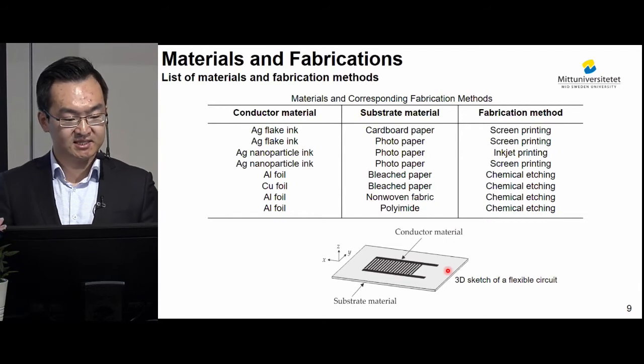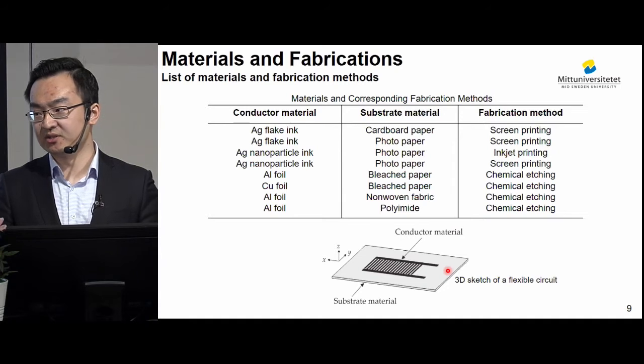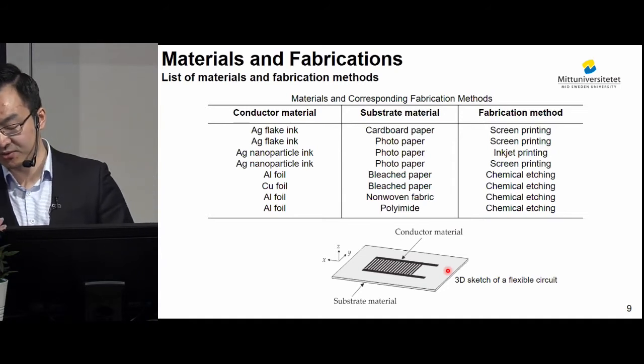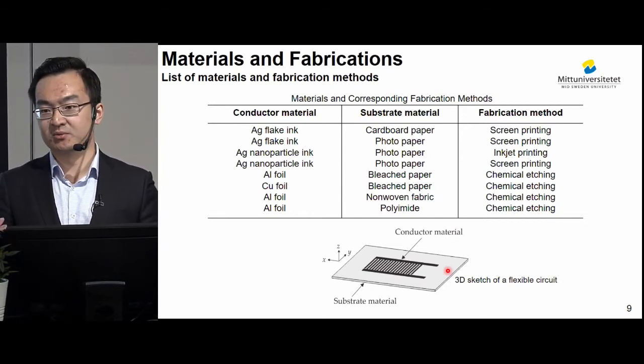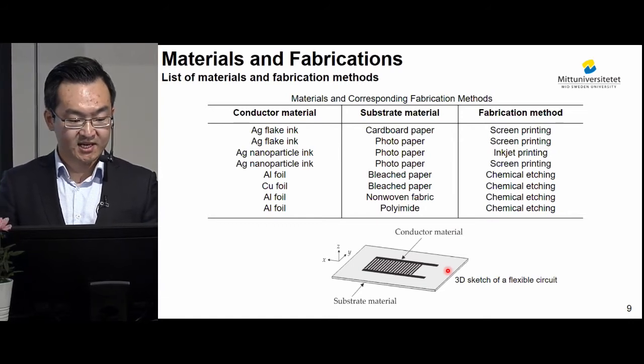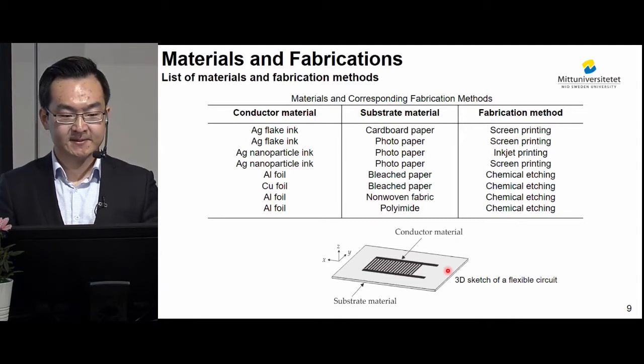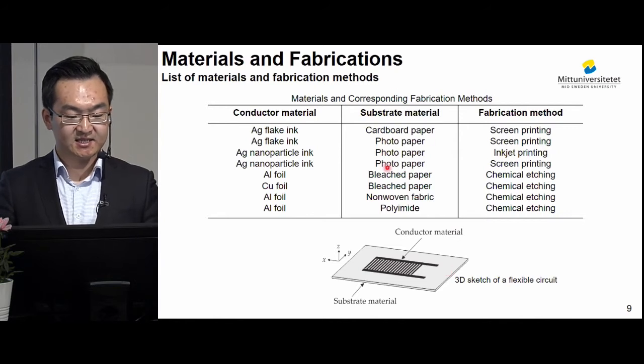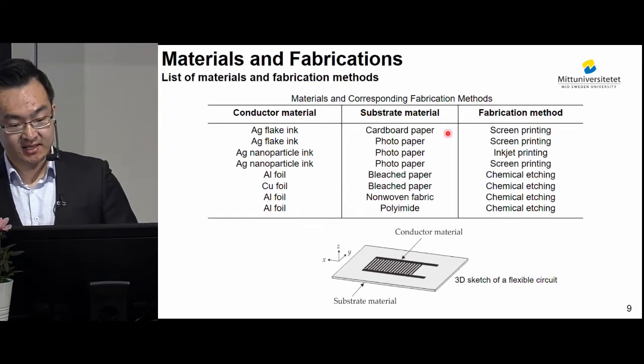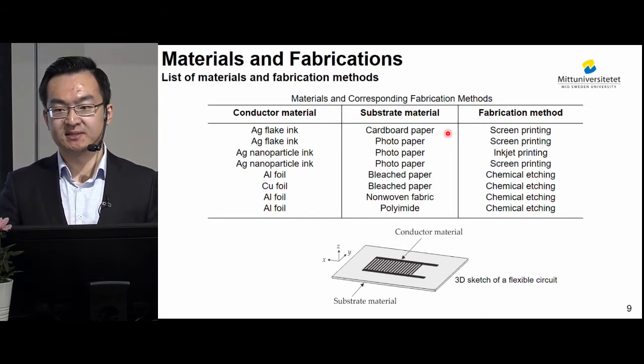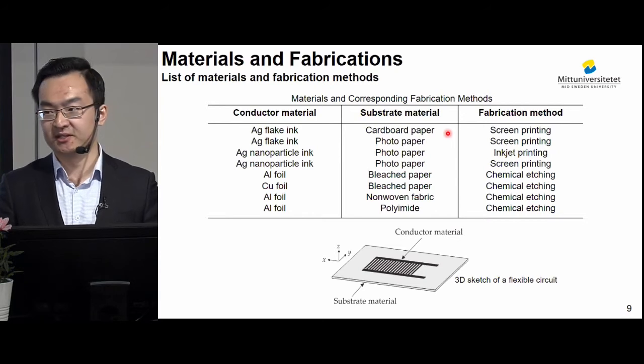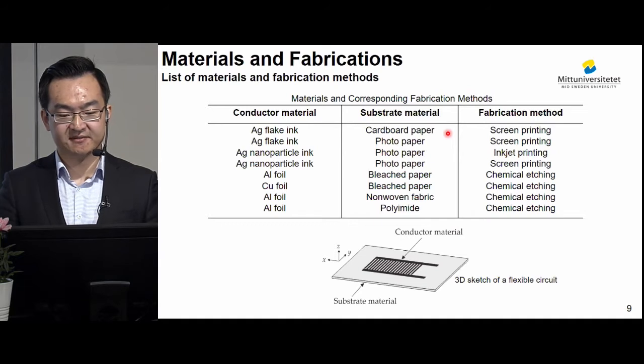For conductor materials, we used silver flakes with silver particle size in the nanometer range and in the micrometer range. And then we also used silver nanoparticle ink with particle size in the nanometer range. And we also used aluminum and copper foils. For substrate materials, as we can see, paper-based substrate is a popular choice for this thesis. In addition to paper, we also used one nonwoven fabric and polyimide. And different fabrication methods were applied to these materials. We applied additive fabrication methods, such as screen printing and inkjet printing, on conductive inks. And we applied a subtractive method. In this case, we used chemical etching on the metal foils.